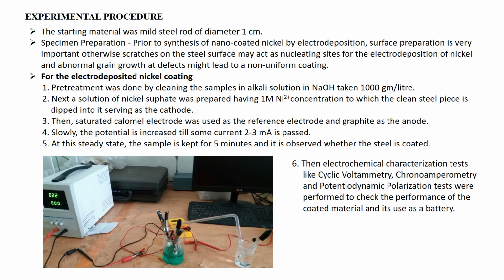Next, a solution of nickel sulfate is prepared with 1 molar Ni2+ concentration, into which the clean steel piece is dipped, serving as a cathode, with a saturated calomel electrode as the reference electrode and graphite as the anode. Slowly the potential is increased till 2 to 3 milliamperes of current is passed, and at steady state the sample is kept for around 5 minutes and it is observed whether the steel is coated. Next, tests like cyclic voltammetry, chronoamperometry, and potentiodynamic polarization tests are performed to check the performance of the coated material as the battery.